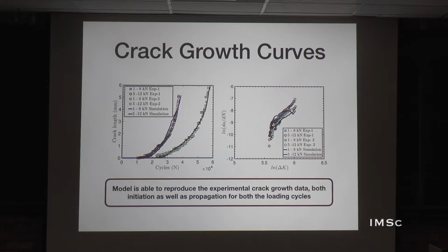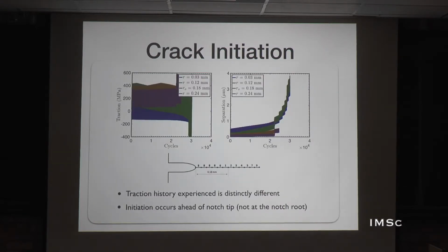Our damage parameter is all dependent on the stress strain field locally, with no connections to what is happening remotely. So these were the predictions, and we were quite happy with that. But what we found very interesting, and this is the part where I would like to focus, is that the initiation of crack actually does not happen at the notch surface, but somewhere inside at an element which is subsurface.